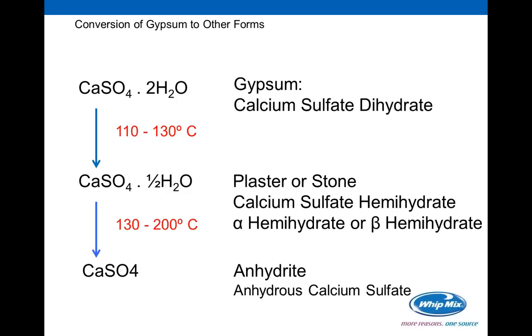Now, if we further refine it by increasing the temperature and continuing to crush this material, we can change it completely from a hemihydrate into an anhydrate, which is the anhydrous calcium sulfate molecule, which you'll notice down here at the bottom is calcium sulfate with no water attached at all. That's when it gets up over 200 degrees centigrade. With that in mind, your responsibility as a dental technician is to take this product that has been changed from its natural state and return it to as close a natural state as we can get it by adding water to it. What it needs is 1.5 water molecules. It doesn't need more than that to do its job, but it does need that 1.5. Now, the interesting thing about gypsum is that because the state that we use the gypsum in is not its natural state, it is going to capture that water from wherever it can.